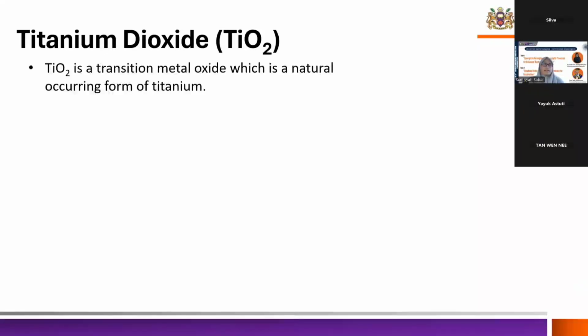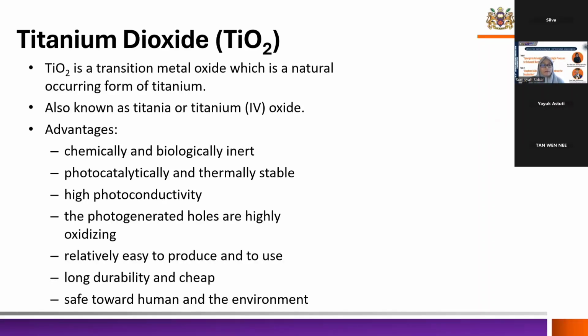So one of the common photocatalysts being used in wastewater treatment is titanium dioxide. Titanium dioxide is a transition metal oxide, which is a naturally occurring form of titanium. It's also known as titania or titanium oxide. It has a lot of advantages compared to other semiconductors. For example, it's chemically and biologically inert, photocatalytically and thermally stable. It has a high photoconductivity, and because of that, it's not only used for wastewater treatment, it's also used for water splitting or hydrogen production, hydrogen peroxide production, and so on.